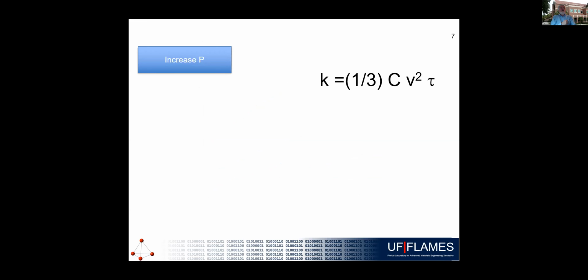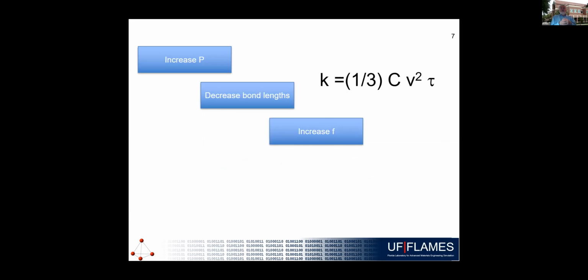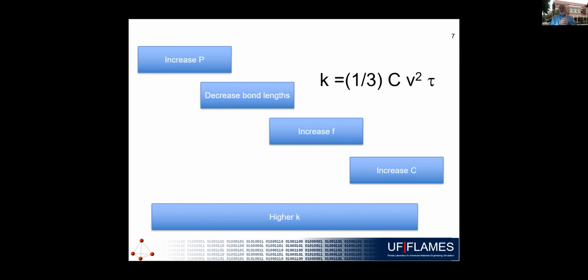We increase the pressure, we decrease the bond lengths. As we decrease the bond lengths, that's increasing the frequency. The coffee cup is fuller or is larger. That means that we're increasing the heat capacity of the system. Its ability to carry heat is increased, and that's giving us a higher thermal conductivity. So this is a very simple way of understanding these simulation results.